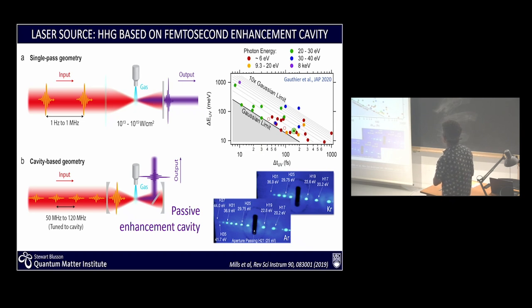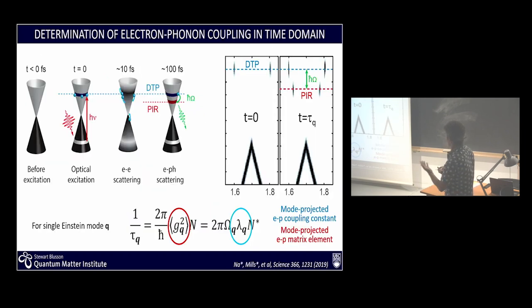This is our data point. So we really try to go for this sweet spot where you have a few hundred femtoseconds and a few tens of meV resolution. So in practice, it's going to be 15 meV resolution in energy and about 150 femtoseconds in time. And why is that important? I'll just give one slide on that.